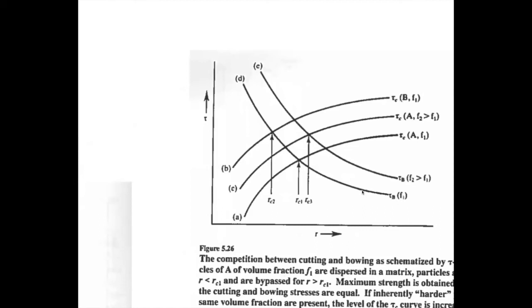So that means the larger we make our particles, the bigger the space, the easier it is to bow around them. So for small particles that are close, it's easier to cut. Big particles that are far apart, easier to bow. And the relationships look like this, right? And so our maximum is when the bowing strength and the cutting strength are actually equal, right? That's where we get the most amount of strengthening. Because if we make our particles larger, now bowing becomes easier and we have a decrease in strength. If we make our particles smaller, cutting becomes easier and we have a decrease in strength.